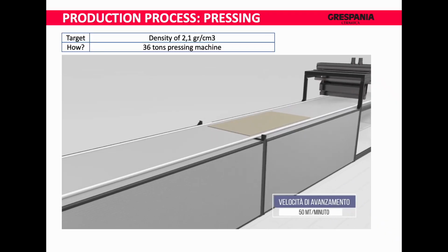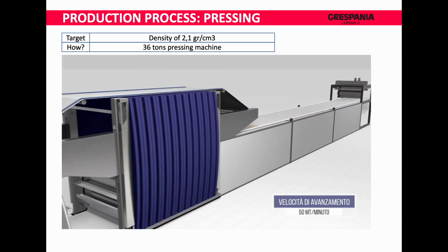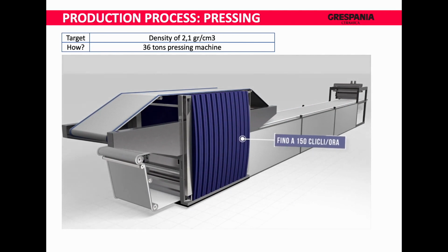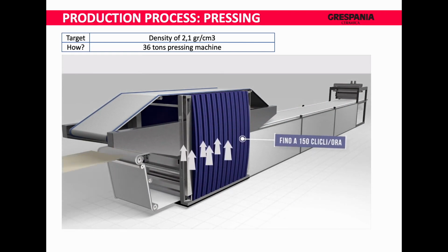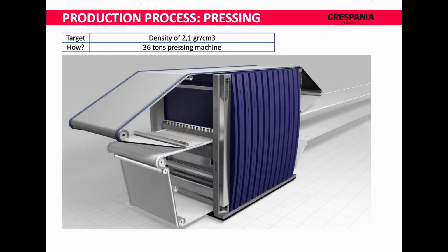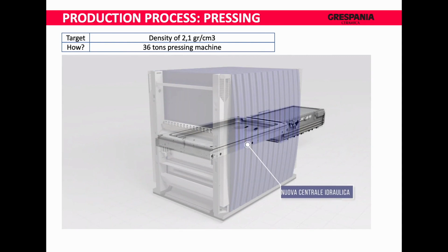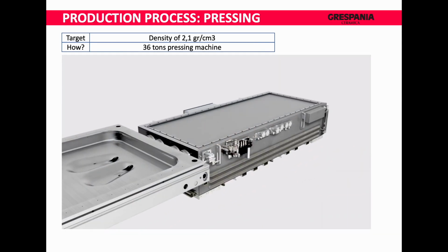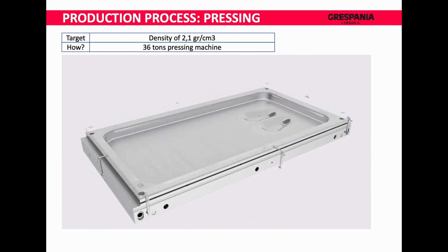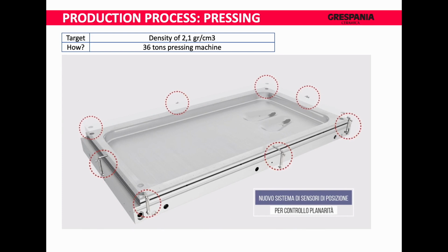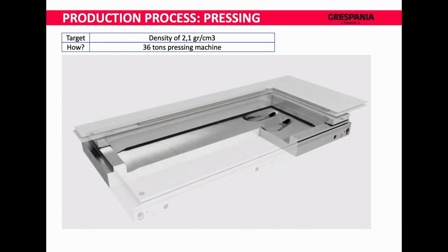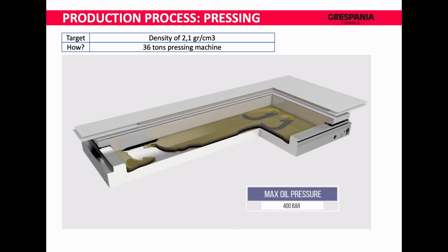This is the new technology. As you can see, we create a layer of porcelain powder that is going inside this pressing machine. We are going to do a vertical pressure upwards. And inside the machine, we will see that the technology is very simple. We have this deposit here, which is basically for oil, and we have that engine that is pumping oil with a total force of 36 tons or a pressure of 400 bar. On top of this deposit, there is a metallic plate of 5 square meters and around 50 centimeters thickness that is leveled by these sensors. And the goal is to fill up the deposit until we transfer all the pressure to the metallic plate.